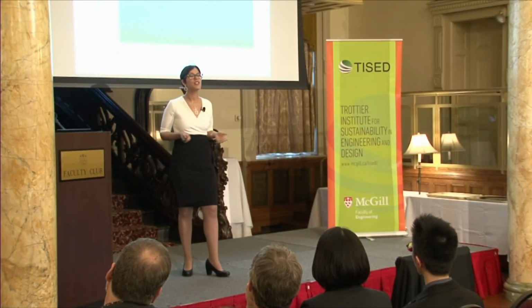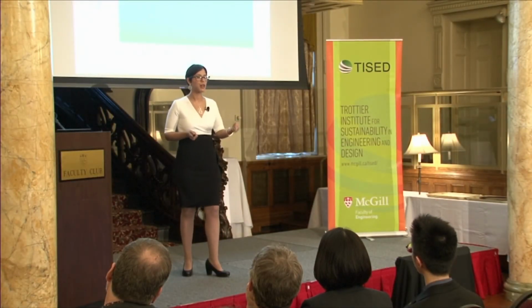We can do that by charging, discharging, just like you would with your phones. If we do that, we can measure the battery capacity, and that is the amount of charge that is stored within 1 gram of the material. This value varies depending on the type of material that you're using. But for lithium titanate, that is what we used, the theoretical capacity is 175 milliamp hour per gram. Now, this is actually quite low, but we have an advantage with lithium titanate, and it's that we can deliver that power, that capacity very fast. We can also charge it really fast, and you want to be able to charge your phones fast, but you want to be able to deliver power fast when you're using something like a power tool that needs fast power delivery.